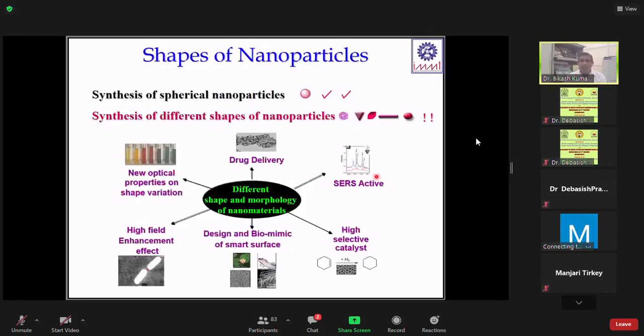And whatever nanoparticles we synthesize, most of them are spherical in shape, because you know the nanoparticle is in a highly energetic state. When the atoms are generated, they undergo nucleation so that they make a shape like a sphere to minimize the surface energy. So there is always a tendency to form spherical nanoparticles.